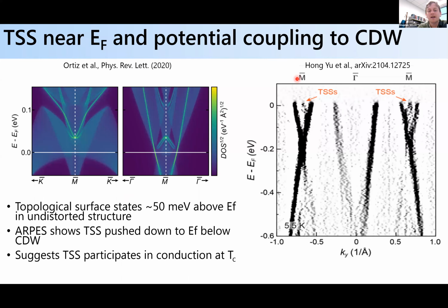And so more recent work by Junfeng He's group has very beautiful ARPES data where they show that if you heat the system up to like 200 Kelvin, they can start to populate states above the Fermi level, and they can see these surface states. And then they cool below the CDW transition, and what they find is that the way the band gaps change as you cool below the CDW actually pushes these topological surface states down to the Fermi level, which is really exciting, right? Because that means that you have topological surface states at the Fermi level as the system becomes superconducting, okay? So the topological surface state should be participating in some way in the conduction as you cool through TC. And so that's of interest to communities interested in topological superconductivity, for instance this proximity induced topological superconductivity via a Fu-Kane type of model.